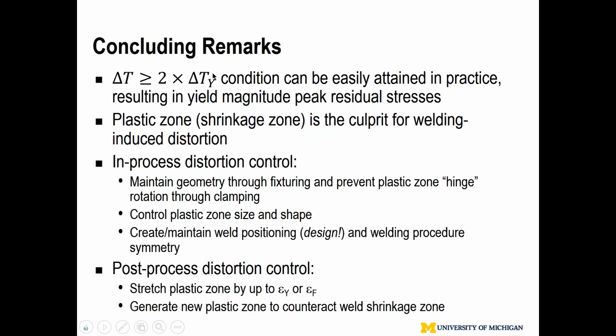The peak value is going to be yield magnitude. Depends on hardening behavior, you can exceed yield, so that's not surprising. So don't get too excited. The question is how to mitigate that effect. So you're going to have high residual stresses as long as you have this condition satisfied. In that case, within the plastic zone, we call it the shrinkage zone, that zone causes all the trouble we are talking about. Small, large, different industries, they introduce all the trouble for us.